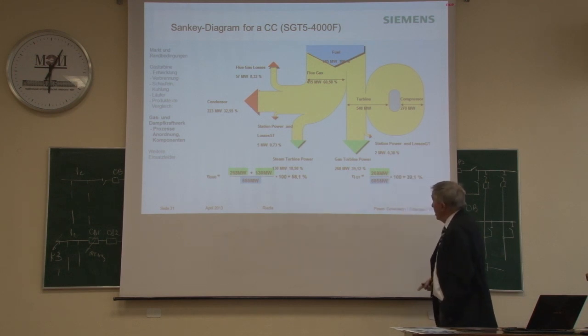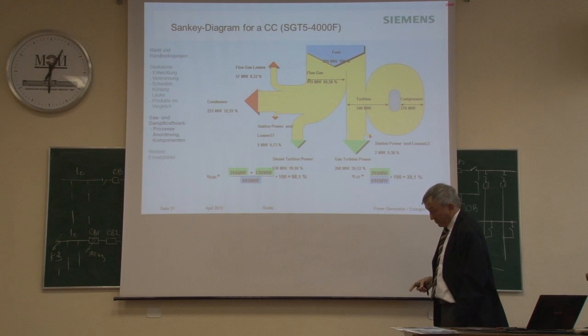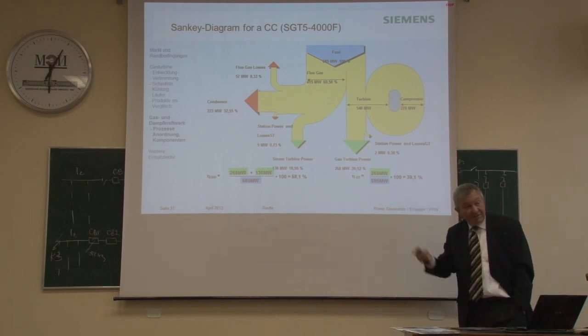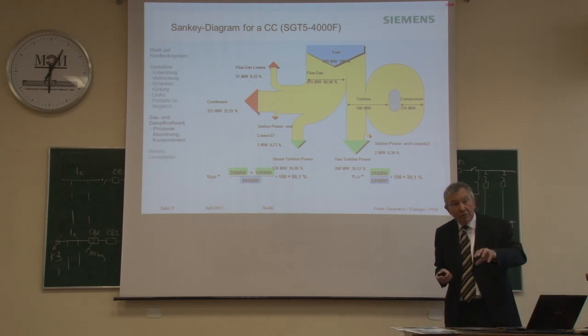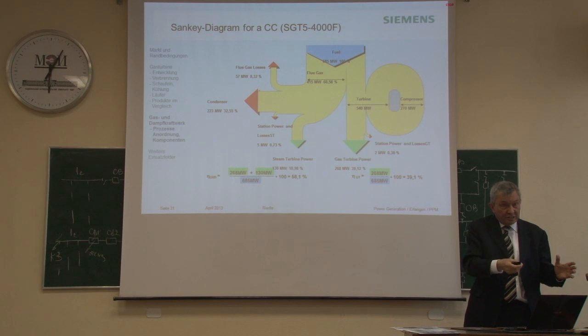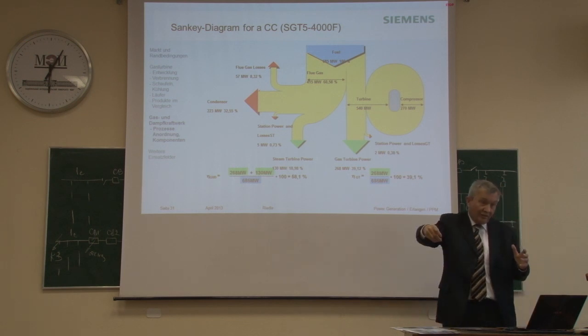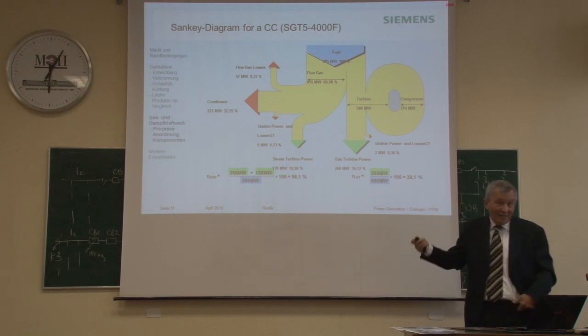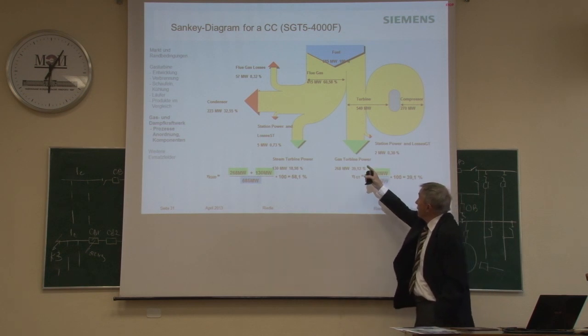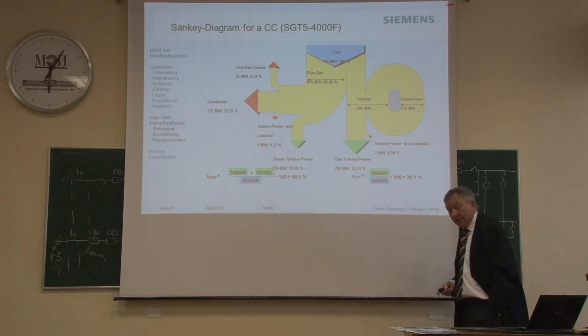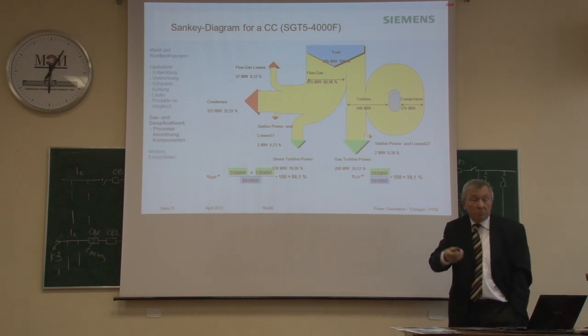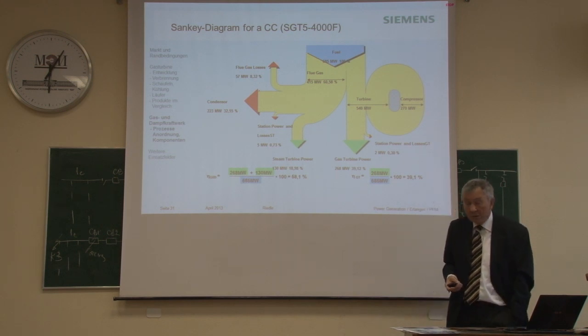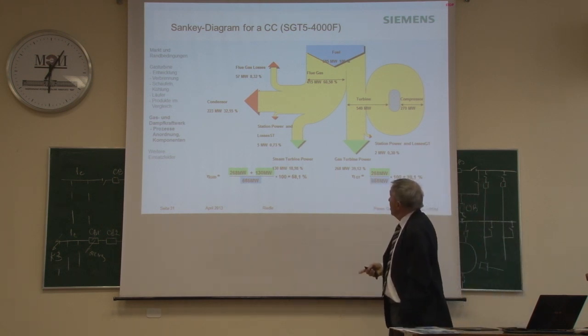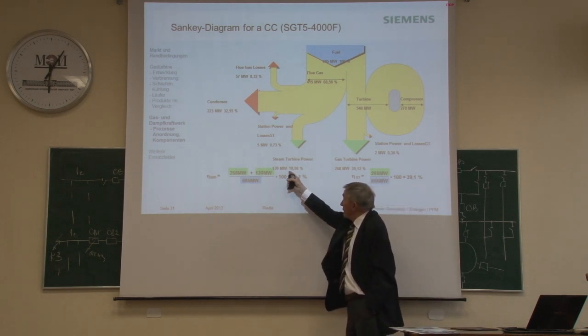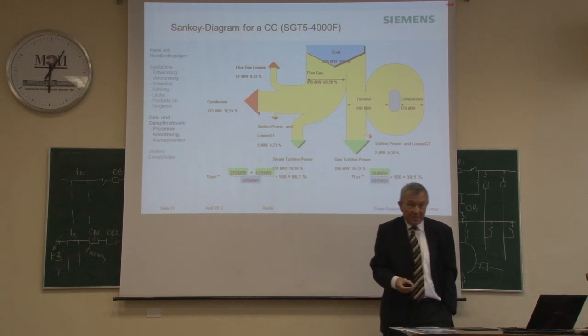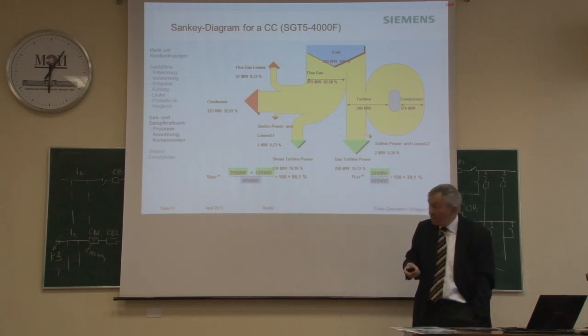The gas turbine has a net output of 268. And why that fat circle? Because about half the power which you generate in the exhaust side of the gas turbine is needed to drive the compressor. So the net, unfortunately, is only about half what comes out. And then in the combined cycle, you take the 60% of the hot gas into a boiler, a waste heat boiler, and provide steam. The steam cycle isn't that efficient, but at least you get in this case another 130 megawatts out without any extra firing, just some additional equipment.